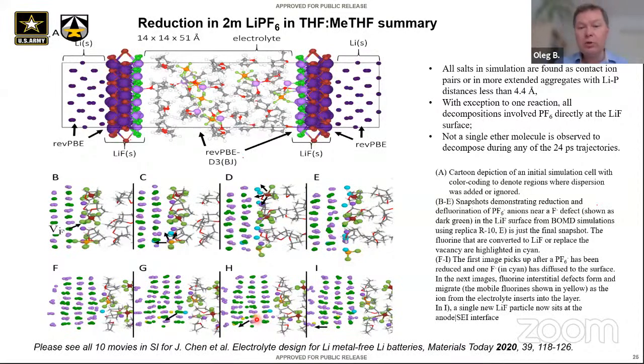And lithium and fluorine diffusion was primarily looked at as a one event, right? Looking at the nanoscale and cooperative events might actually explain why LiF is actually not such a bad conductor, and doesn't matter how it rearranges. If it's on a nanoscale, it can rearrange any way you want. You just need to have relative motion of lithium and fluorine.